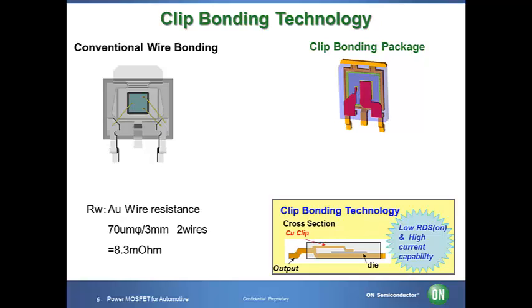Formerly, we used wire bonding technology using gold, copper, or aluminum wires in order to connect each electrode on the silicon chip in the package. However, since each wire is relatively thin, it is difficult to allow higher load currents without excess losses. We successfully reduced the on resistance and realized better thermal conduction by connecting each electrode directly with a copper clip, overcoming those disadvantages. The structure of the clip bonding technology uses a copper plate with a wide cross-section area. This enables the increase of total full load current without concern for the fusing current that occurs in conventional wire bonding.